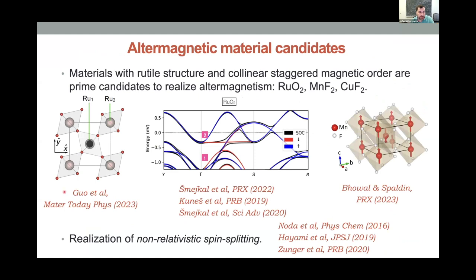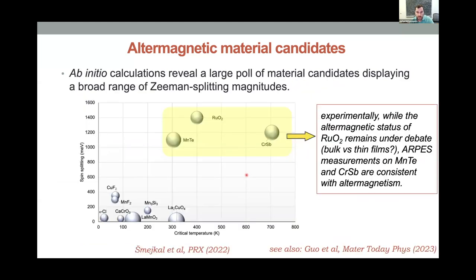And the main idea is now that with the symmetry considerations that are prescribed with this spin group analysis, you can find materials from databases that have these properties. And as I believe was discussed before, rutiles are one of the main candidates. Manganese difluoride has been very widely studied since the 80s. Ruthenium oxide, there are still some controversies of whether it's even magnetic or not in stoichiometric form. And right now, there are, I would say, three.